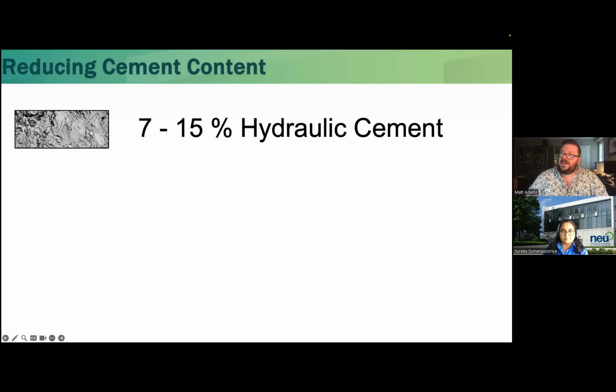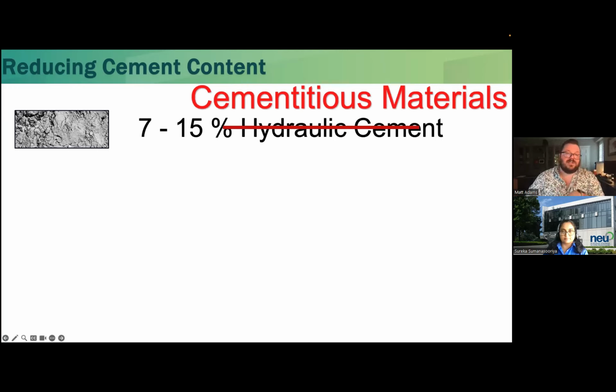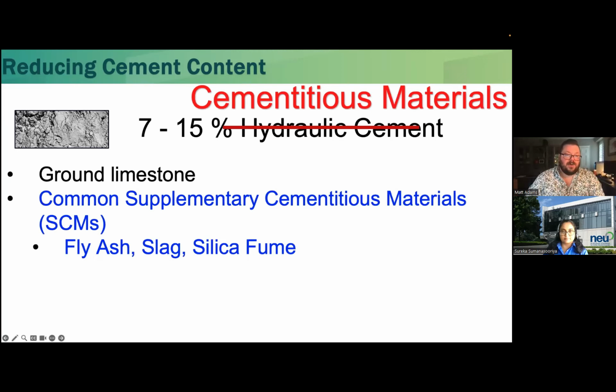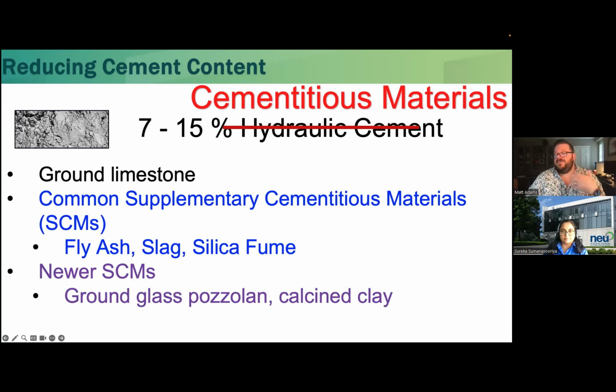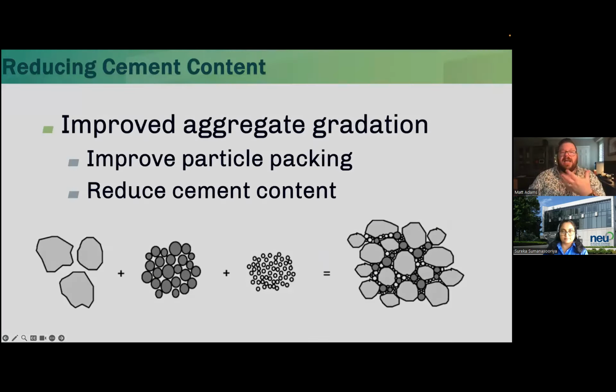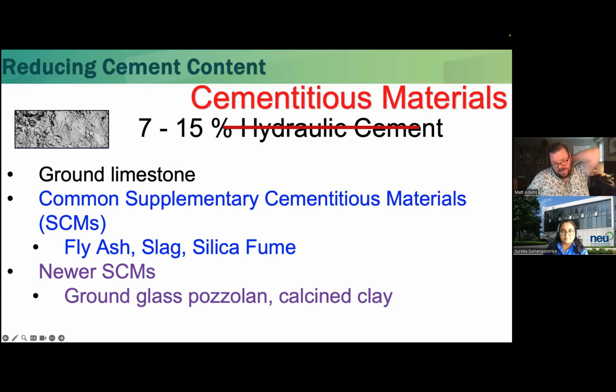So how do we reduce our cement content? You know, the amount of cement in a concrete mixture is about 7 to 15%. If we can try to step away a bit from using all Portland cement, which a lot of people have started to do, and think of it as just total cementitious materials, we can start to include things that have much lower embodied carbon. So ground limestone, common supplementary cementitious materials, though we know that there are potential access issues for fly ash and slag on the horizon. And then we have newer SCMs that are coming onto the market, like ground glass pozzolans and calcined clays. Not going to get too deep into what these are, but there are many options for trying to reduce the total amount of cement in your system.